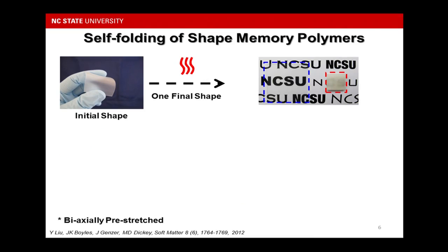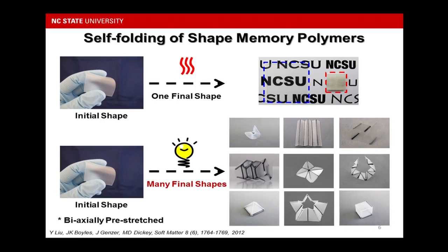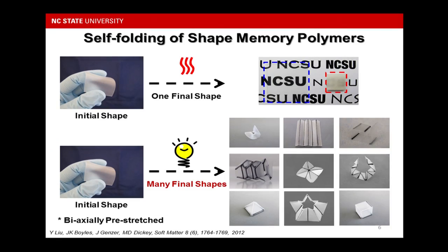I will explain a little bit more about these materials. This material is a biaxially stretched polymer, which is flexible and transparent. Maybe you have heard of the children's toy called Shrinky Dinks. This is one example of that. Usually, when you put it in the oven, applying uniform heating, you get a single final shape, which becomes smaller. In this case, it's about a 50% shrinkage. However, in our method, we use light and print black ink on these polymers. In this case, we can achieve many different origami structures by applying different hinge geometries or patterns. This process can be further controlled by controlling the geometry of the hinge and also the hinge width.